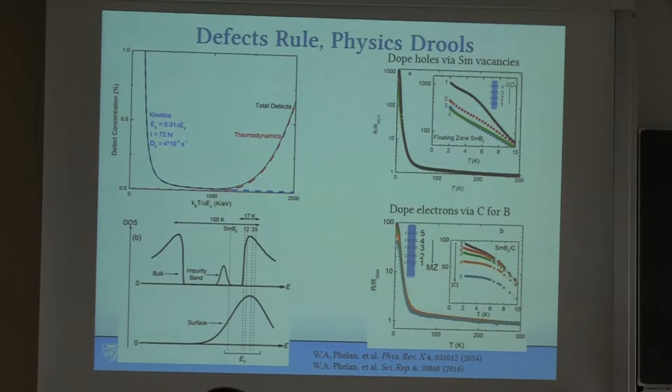Well, what is it? So I am now summarizing effectively two years of work by Syed and one of my other former postdocs, Adam. When you make materials, they're never perfect. Here's the little reason why. If you use it at low temperatures, kinetics come into play. Basically, the atoms don't have time or they don't have the energy to get into the right position. So you get a large defect concentration. On the other hand, at high temperatures, entropy wins, and so that T delta S term really wins. And so you get a large number of defects at high temperatures. So actually, the name of the game in much of this chemistry is to control the defects, control the type and number of defects and see what happens as you systematically vary them.